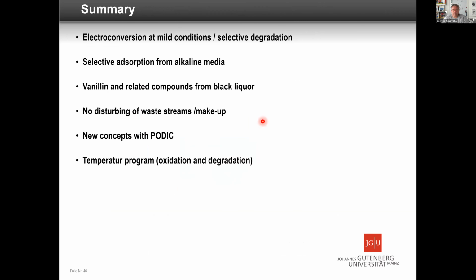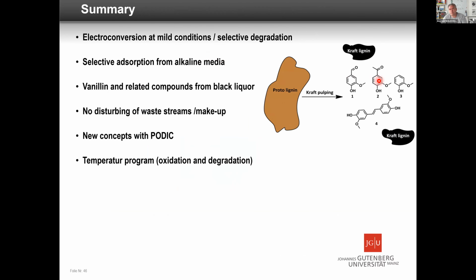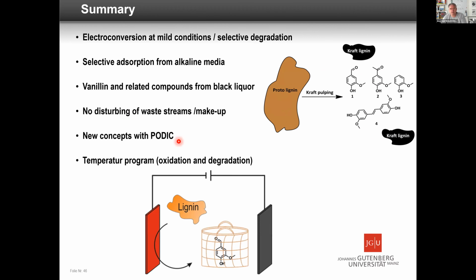I have shown you a lot of things today, but black liquor is very appealing, interesting things, and in combination with electrochemistry, you can do a lot of things out of it. There's one way to get these small molecular weight systems out of it, but the problem is you have to separate them off. And if you make something, you cannot only extract it, you need something which is compatible with a paper mill. And one possibility is that you just catch it out of the system with this resin, or you can pump it out in a kind of bypass, and then you fix the desired molecules, and then you already get a relatively well-concentrated product mixture out of it.